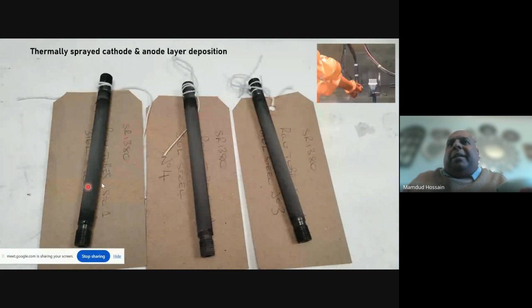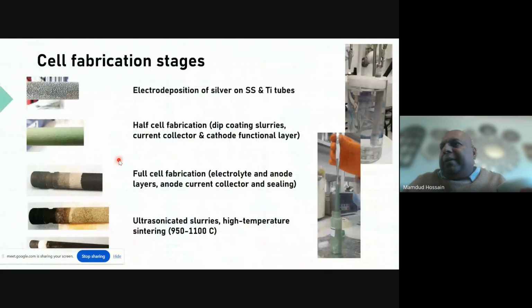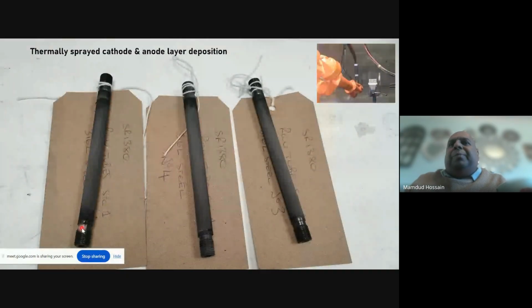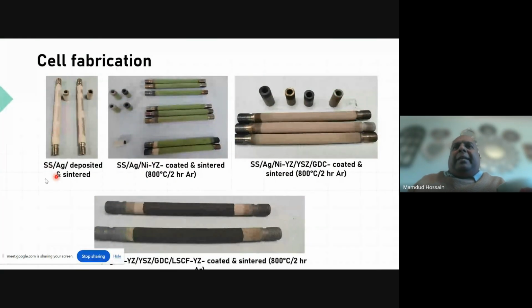So we ended up with this type of tube. We also used some thermally sprayed cathode and anode layer deposition. So in our lab we did dip coating, and we also sent out this tube to an external company. They did the thermal spray, and we wanted to look at which process gives you more stability. So again, cell fabrication: we gradually have silver on stainless steel, silver deposited, sintered, then nickel YSZ coated and sintered, another layer YSZ and GDC, one coat and another coat, and finally LSCF YSZ coated. Okay, so you are building up from our tube different layers on top of each other to create our electrolyzer.